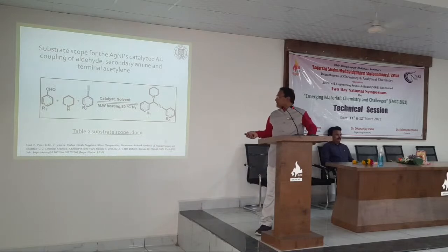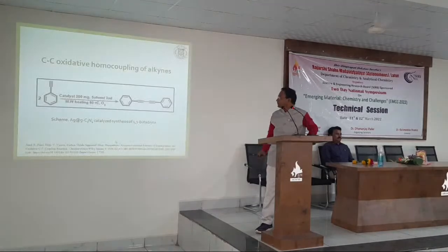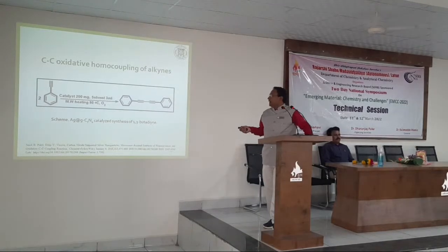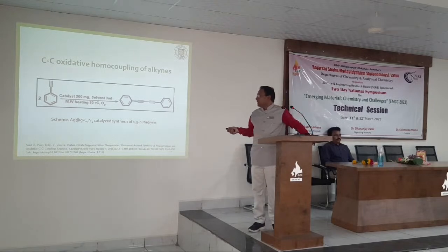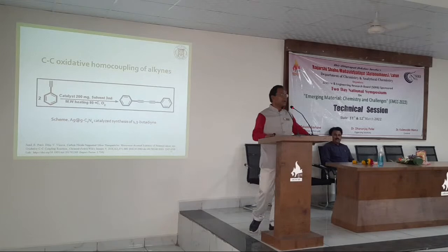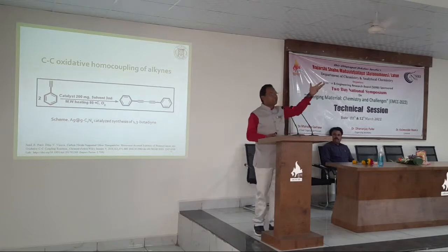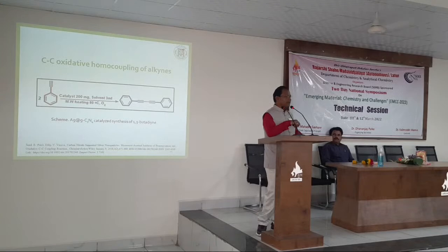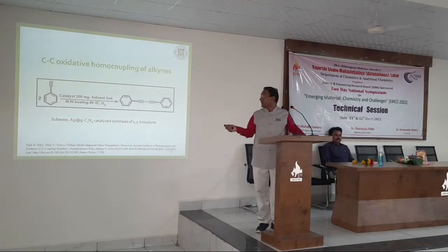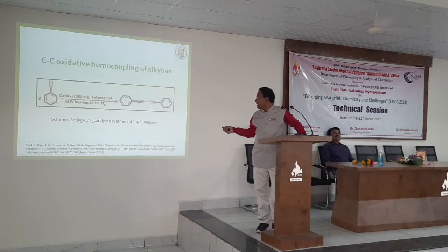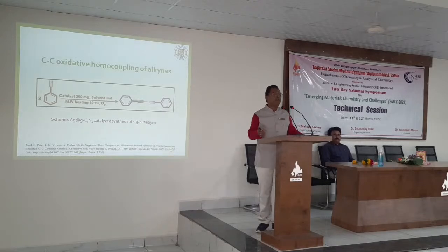So it was optimized, and different derivatives of the aldehyde and the acetylene were taken, and accordingly the propargylamine was synthesized. Here again it was carried out in the atmospheric condition. The previous reaction we carried out in a nitrogen chamber. In the presence of oxygen, it is the homocoupling, so 2 moles of the terminal alkyne were taken, and here the C-C coupling took place to synthesize the 1,3-diyne.